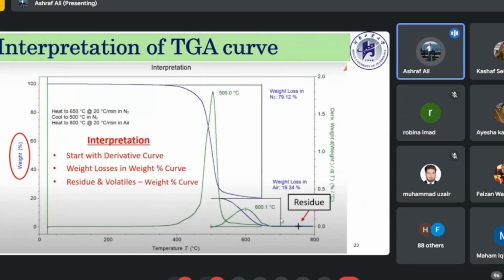Now, if you look toward the residue here, when the weight does not reach 0%, it means that there is some residue, and residues are those materials which do not decompose even at a very high temperature, and it may be carbonate, or some ceramic material or silica, something like that. So you can find out this information: the weight loss in the sample using nitrogen up to 505 degrees C is about 79.12%. The weight loss in air is about 19.34%, and how much is the residue? It is about 1.54%.